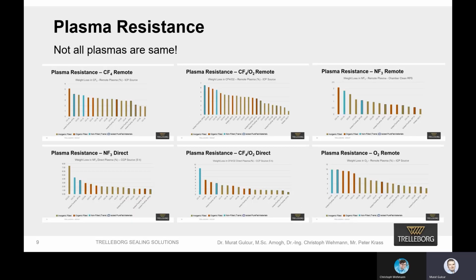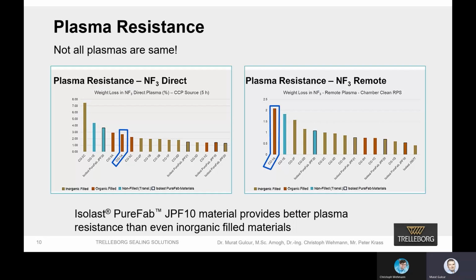So most of the seal suppliers, they show this kind of bar charts, benchmarking tests in different kinds of plasma sources and different chemistries. And when I show these kinds of slides, I always say that not all plasmas are the same. So I'll just take two examples. Both are NF3 plasma, which is commonly used, but on the left-hand side is direct plasma, which is more ion-rich, and on the right-hand side, NF3 remote plasma, which is radical-rich. And let's see the results a little bit more in detail.